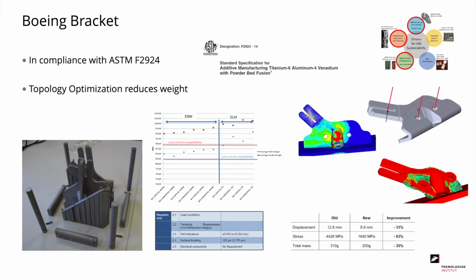We also showed that you could use this phenomenon called topology optimization, where you simulate the part and the forces on the part, and through an iterative simulation process you remove all of the material that is not needed. In this case, we could make it stiffer, we could make the displacement smaller, and we could reduce the total mass by 35%, from more than 300 grams down to about 200 grams.